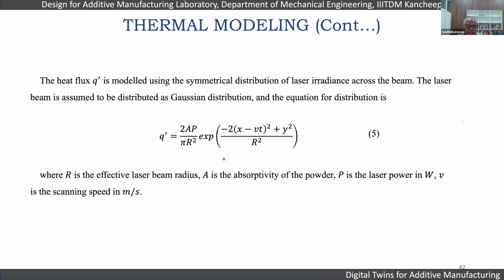And we also calculated the absorptivity based on a particle dynamics model. The absorptivity typically influences the total energy input. So from the particle dynamics model, we calculated the absorptivity, and that is effectively used here as the absorptivity of the powder. And then we have used this expression with laser power, and Q prime is typically the distribution of the heat flux, which is to be input in ANSYS.